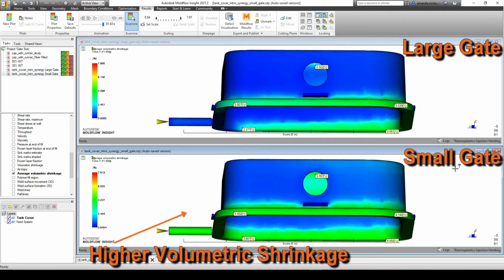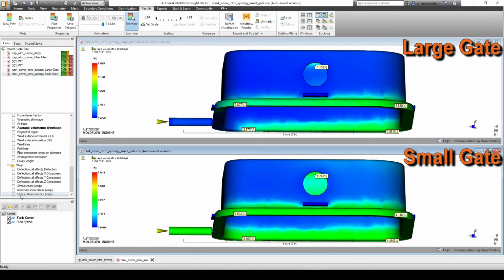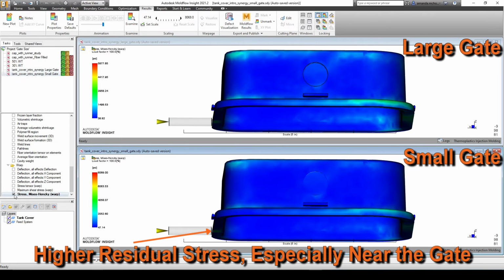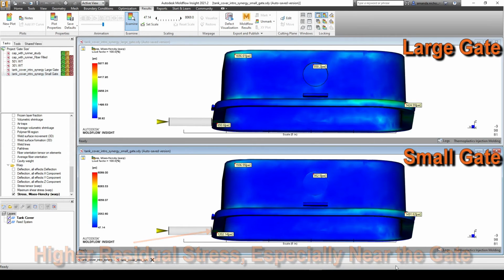As a general rule, the upper limit for gate thickness is 80% of the part's wall thickness at the gate location. However, a larger gate will be more difficult to remove after ejection and could cause a larger vestige on the part's surface. Therefore, gate selection and sizing need to balance the customer's requirements for both part aesthetics and the ability to develop a robust process.